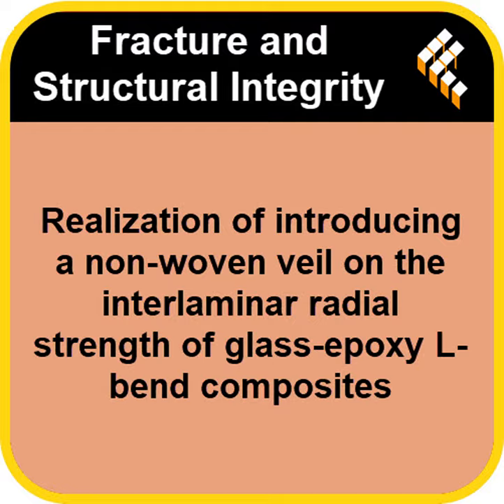That makes sense. But here's where it gets weird, right? Because you'd think, okay, 15 g/m² is great, let's add more. What happened with the 20 and especially the 30 g/m² carbon veils? This is the real surprise, the paradox. Adding more carbon didn't just give diminishing returns, it actually made things worse. Significantly worse. Worse than the 15 g/m² one. Way worse. The sample with the highest density carbon veil, GEC-30C, had a CBS that was 43% lower than the champion 15 g/m² sample. A full 43% weaker? By adding more reinforcement, that seems completely backwards.